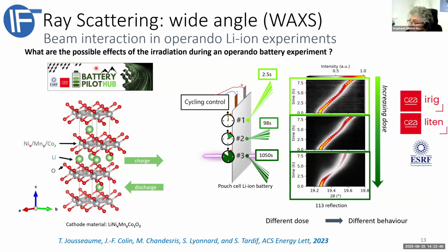Another example, just to mention that when you are looking at structural properties in battery materials, you have to be careful about radiation damage. So, in a polite way, we are talking about beam interaction with the sample. To get reliable data, you have to make sure that the dose, the amount of energy per second you put into the sample, can't change the chemistry and also the structure of your material.